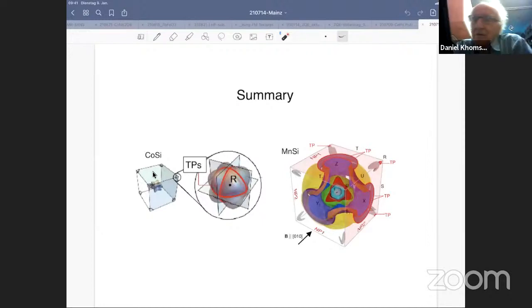Thank you. I have a rather general question, actually. Your main problem was to check whether some topological features are protected by particular symmetries. Fine, you find many cases, and indeed, if you keep the symmetry, then these crossing points in the band structure, for example, are really protected. But the point is that it's very rarely checked, and I don't know whether it's really a problem for you, but in general, whether this particular symmetry may be spontaneously broken, whether the protection will survive, for example, some interaction. For example, you consider in the very beginning a line of Dirac nodes when we have two paraboloid kind of crossing.